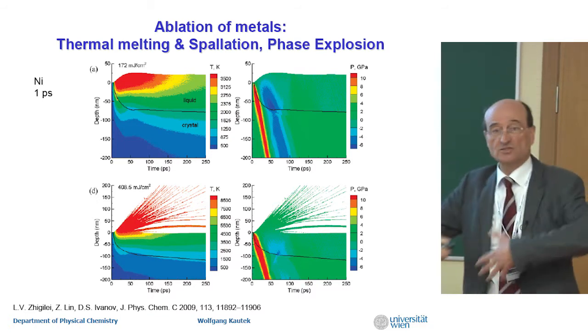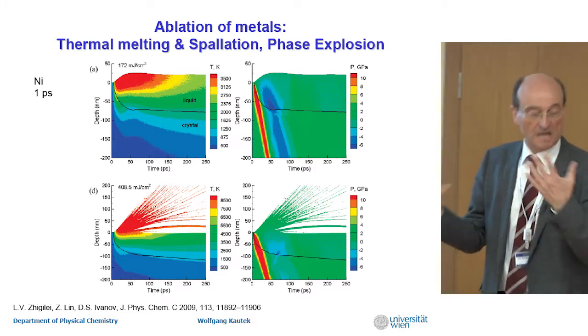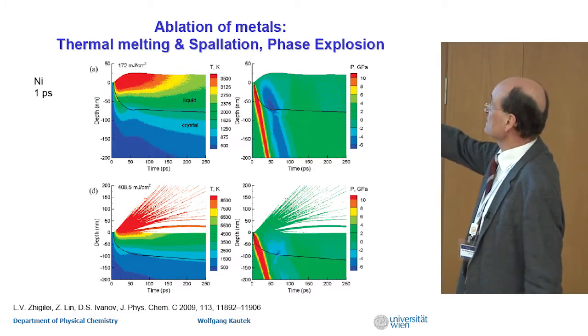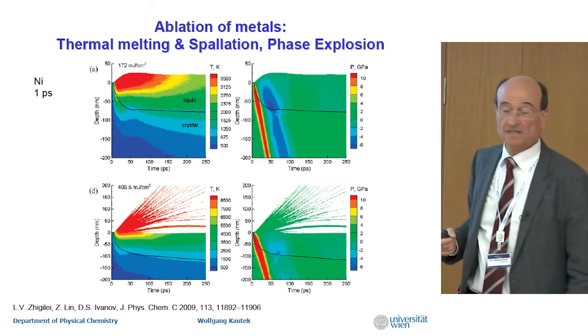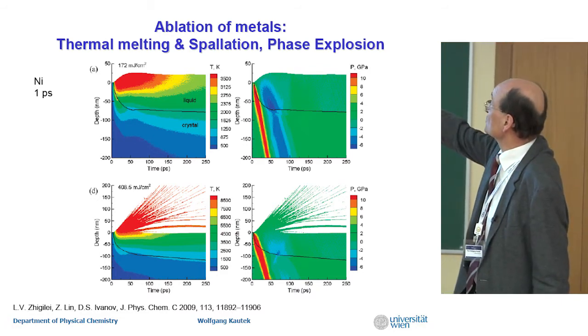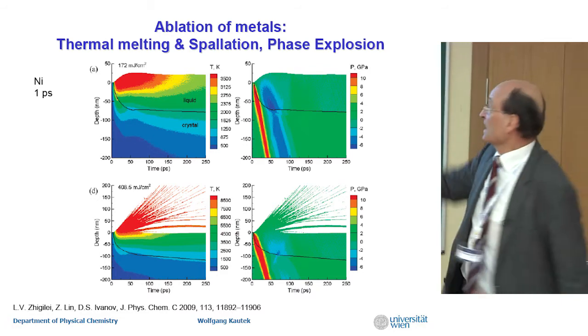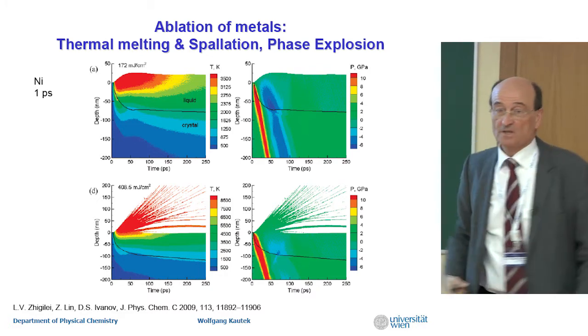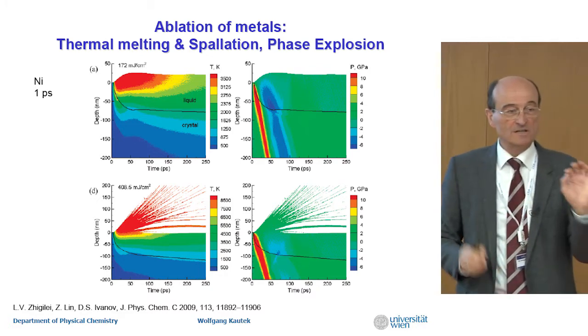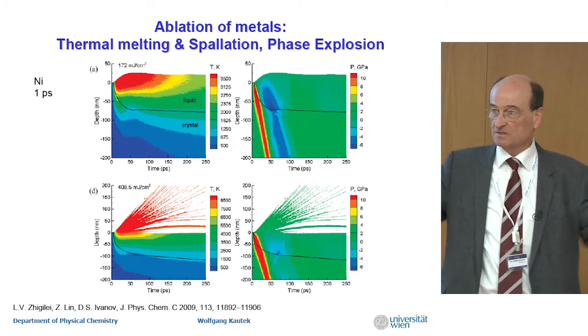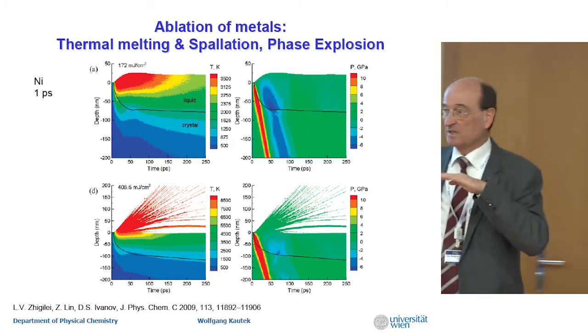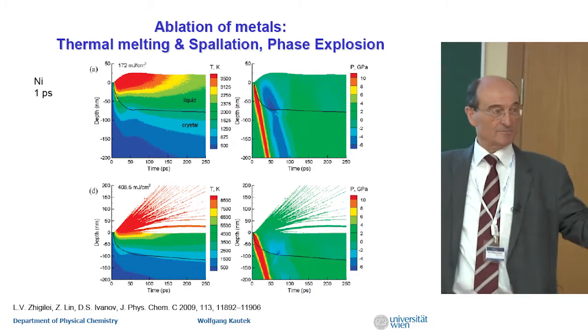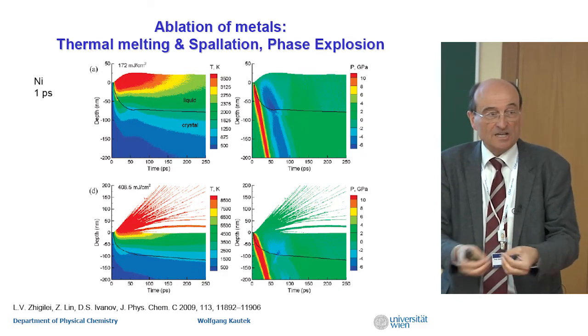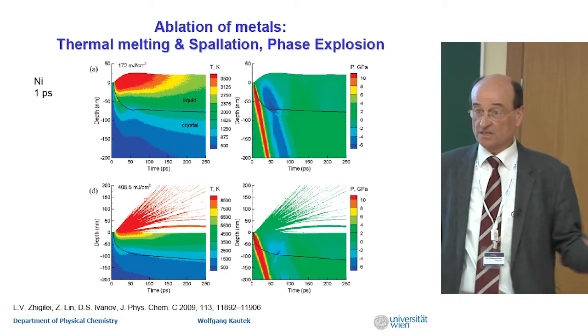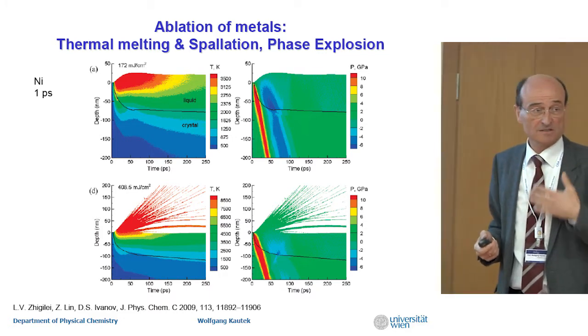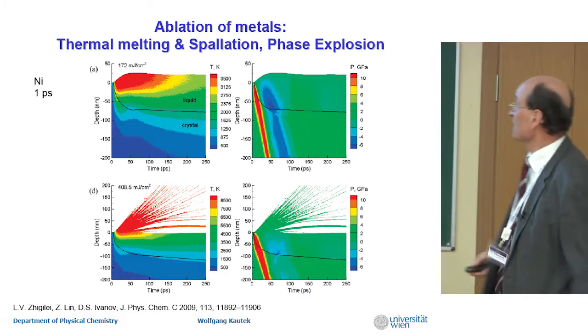And you have an expansion of the material: melting, crystal, liquid. And what is very interesting, you have a rarefaction, so you have underpressures. And this underpressure here may tear apart the material and end up in bubbles. And there's a big discussion going on that in materials which were not evaporated, you're creating nanobubbles in the bulk, which changes the physical properties of metals drastically. But this is still under discussion.